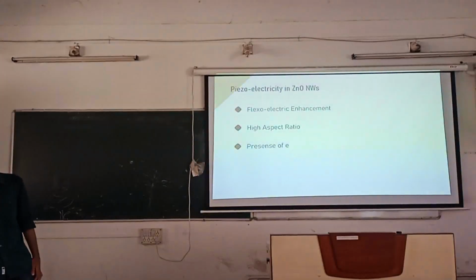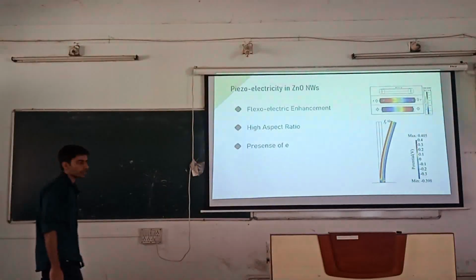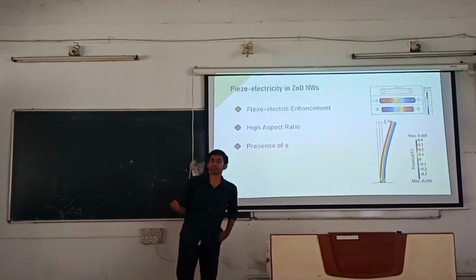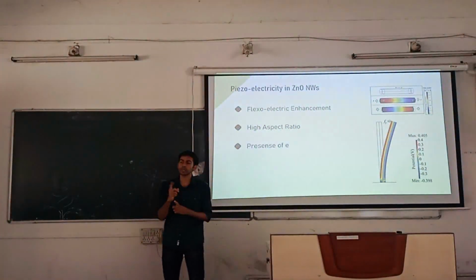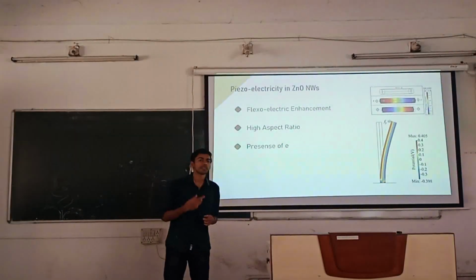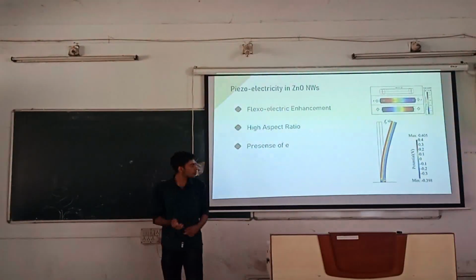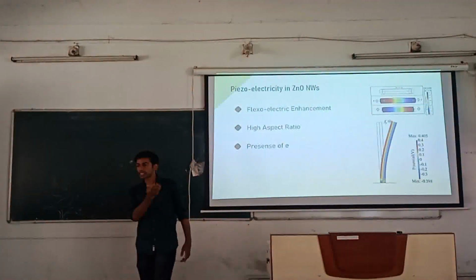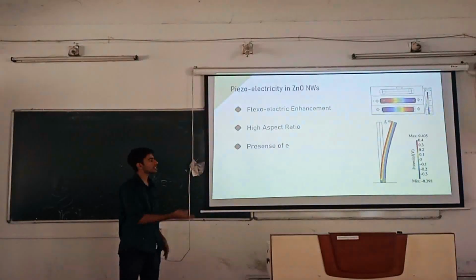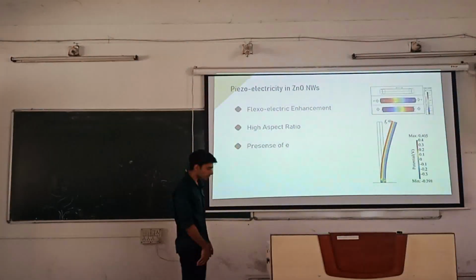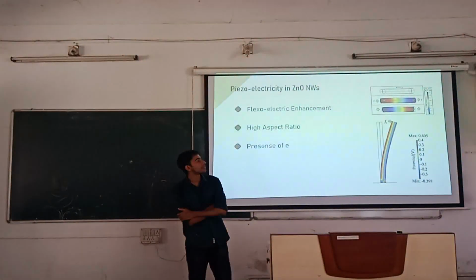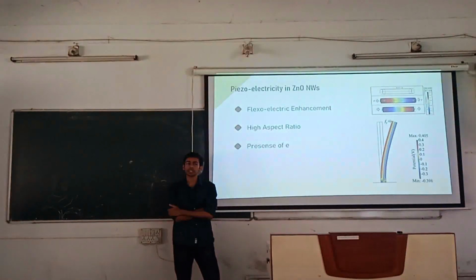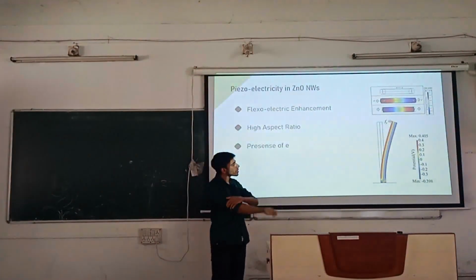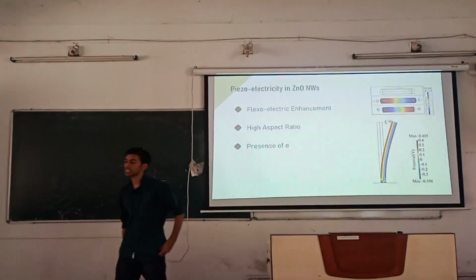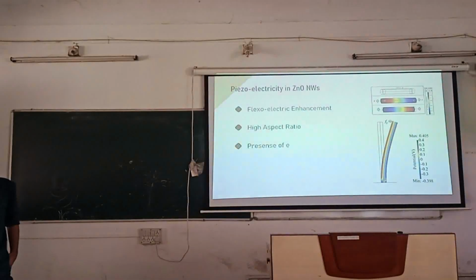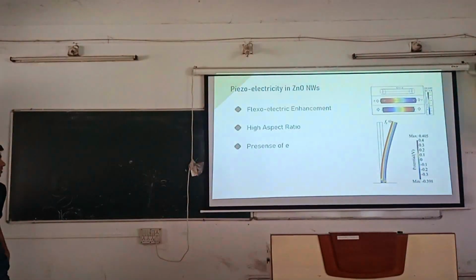But apart from the piezoelectric properties, they also show a property of flexoelectricity. Normally a crystal is very strong, we cannot bend it. But since this has a very high aspect ratio, it's possible for us to bend this crystal. So when it bends, it generates a voltage, apart from the piezoelectric voltage, which is called flexoelectric voltage. The flexoelectric coefficient of zinc oxide is very high. You can generate like 0.405 volts from just flexing it. No other crystal offers such a high flexoelectric coefficient. So apart from the piezoelectric effect, we also have the flexoelectric effect in zinc oxide nanowires.